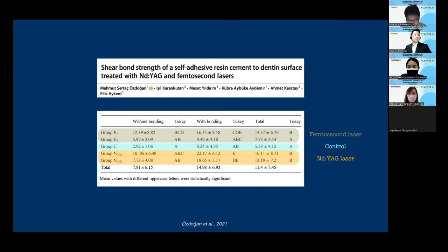But some methods are suggested to enhance the bond strength of self-adhesive resin cement. Özdoğan and colleagues studied the effect of Nd:YAG and femtosecond lasers and universal adhesive on the shear bond strength of self-adhesive resin cement on the human dentin surface, and this study found that the use of laser combined with applying 10-MDP containing universal adhesive drastically improved the adhesion between dentin and self-adhesive resin cements.